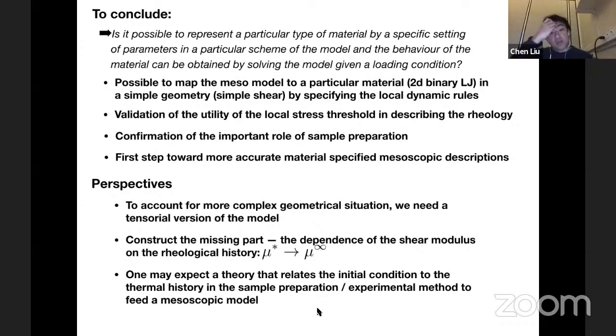So one may expect to develop a theory that relates the initial condition to the thermal history of the sample preparation. What we do here is with an MD system, where we can measure local stress very easily, but in experiments, one could expect that in the future, maybe we can develop more methods to measure local stress or local quantities to feed the mesoscopic model to provide a prediction of the real system. So that's my presentation. Thank you for your attention.